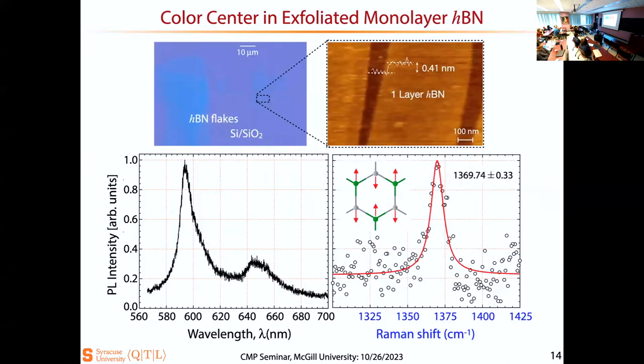Yes, so over the years, I have worked with color centers found in literally one layer of atoms, as you can see here, and then how we confirm it is really a monolayer using an AFM. But doing an AFM on a monolayer, we have to be very, very careful. And then you can also do Raman. Raman is a little bit more stringent, okay, by looking at where the peak is from a monolayer and how the peak shifts when you go from one layer, two layers, three layers.